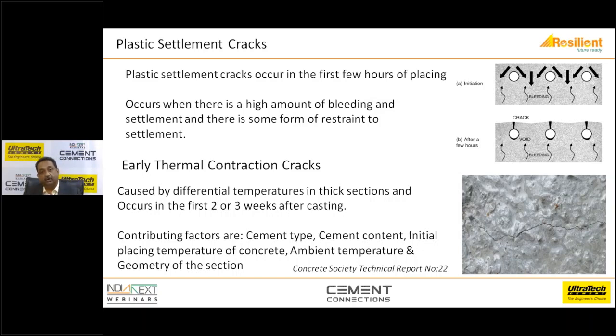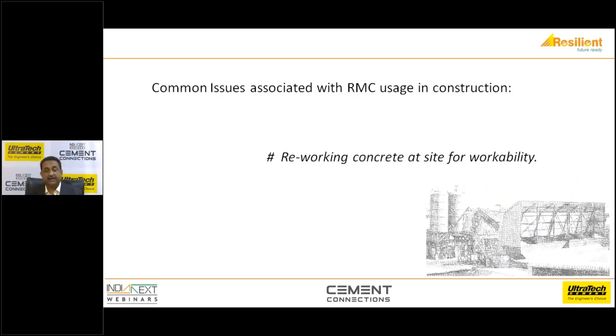Initial placing temperature of concrete, try to place the concrete, especially in raft, maybe around say 25 degrees centigrade, or even better if you can go below 20 degrees centigrade if the thickness and the section is too large. So there are ways in which you can overcome, but again, this is a combination of specifications, the material used, and communication with the specifier, the user, and the ready mix player is extremely important to avoid these kind of issues.